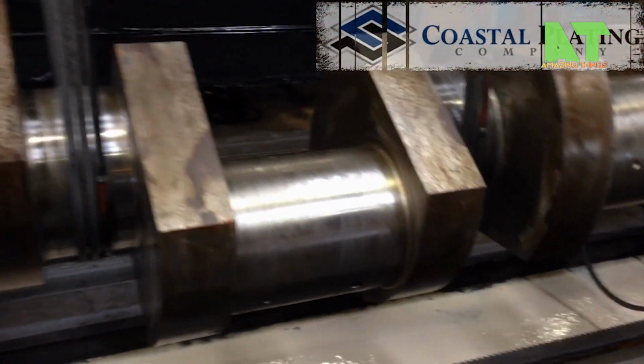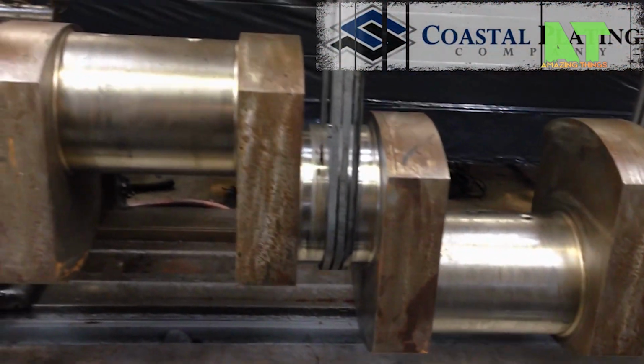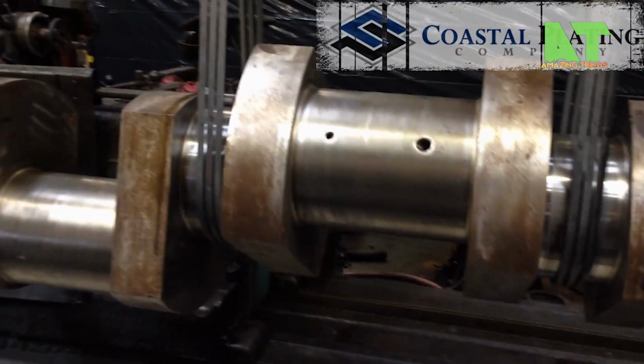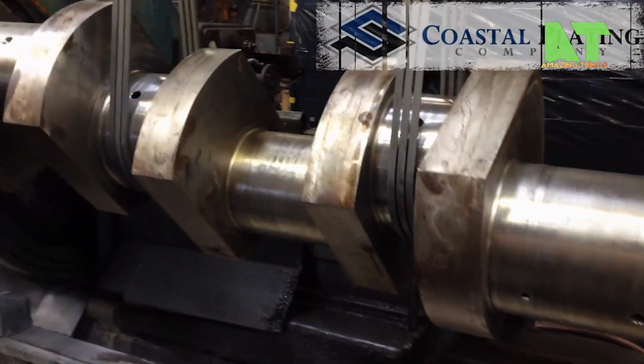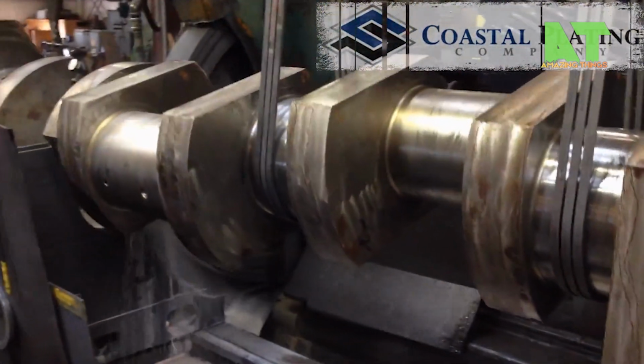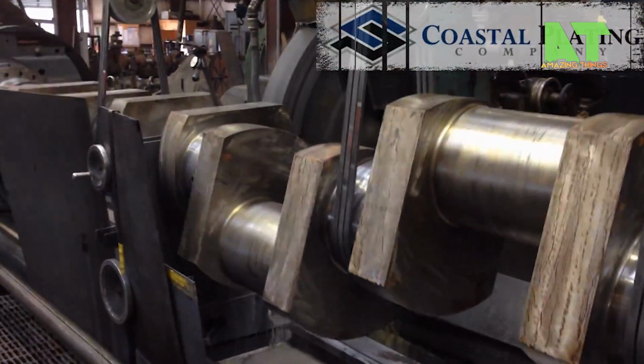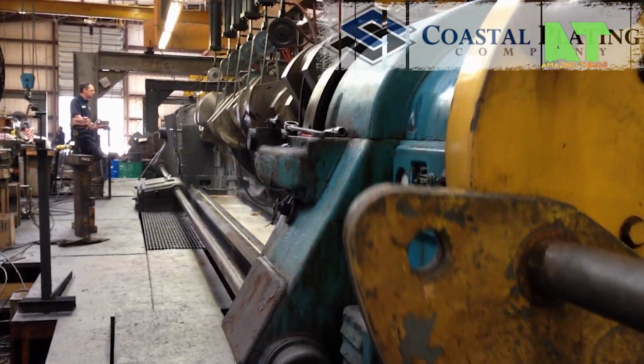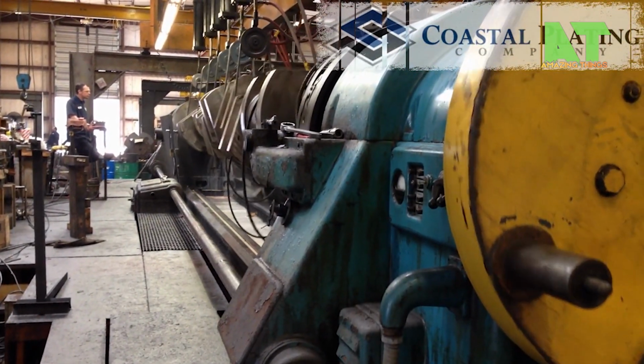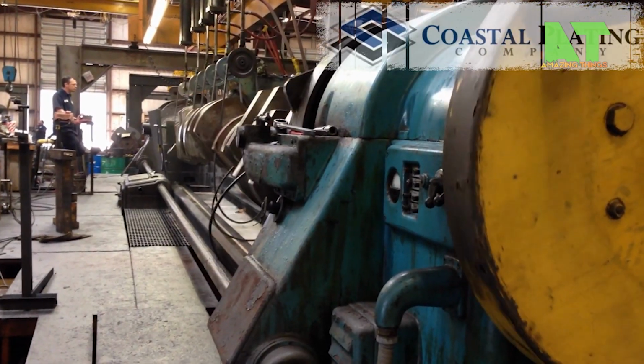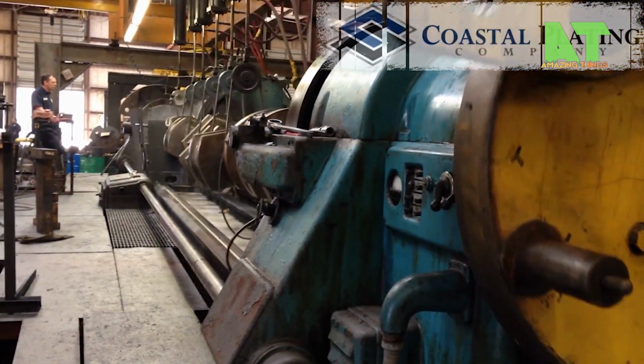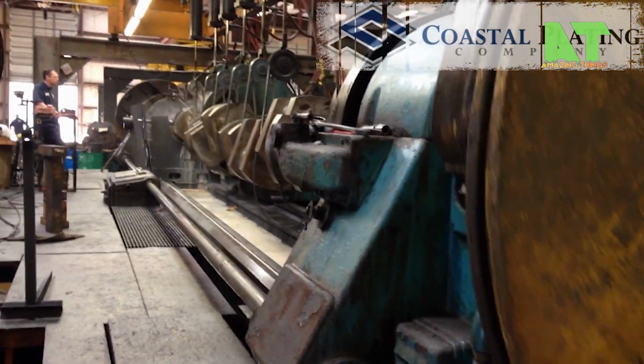After plating, the journals are ground and polished back to their original or sometimes tighter tolerances using a precision cylindrical grinding machine. The finished surface must meet surface finish specifications, measured in microinches, typically in the range of 8 to 16 Ra. That's a mirror-smooth finish that allows the bearing to float on a thin oil film at high RPM without metal-to-metal contact.